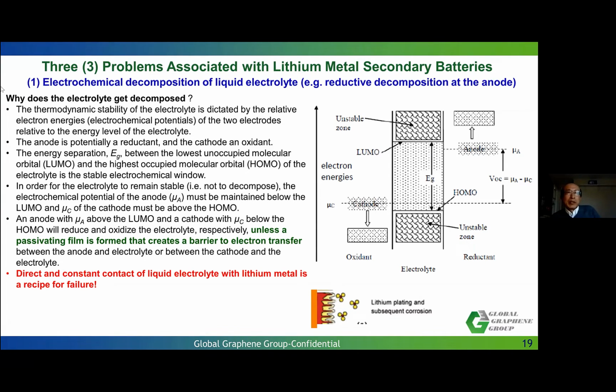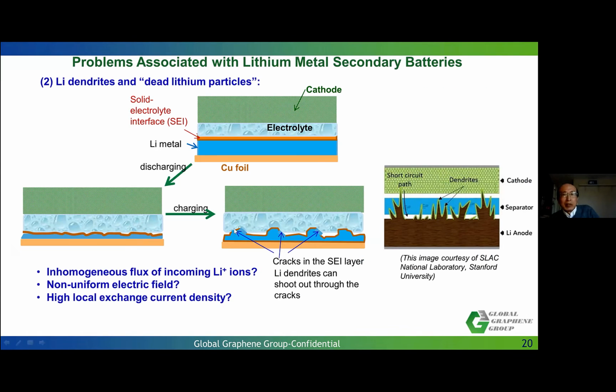Another issue is the so-called lithium dendrite. In theory, when you deposit your lithium metal from the cathode back to the anode, presumably you should form a homogeneous deposition of your lithium metal, but things don't go that way. It goes in a very inhomogeneous manner, and eventually some dendrites protrude out just like this, and penetrate through your separator into the cathode. That creates internal shorting, and presumably that can lead to explosion as well.